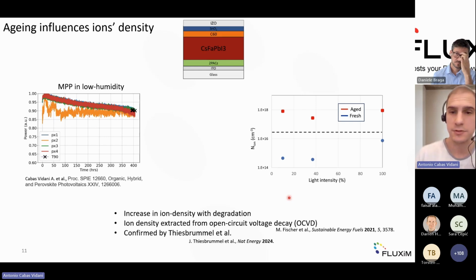So what we did, we performed open circuit voltage decay measurements where you shine a light on the sample, you turn it off, you keep the sample at open circuit voltage and see how this decays. Now with a rather complex elaboration of the data, you find everything in the paper from Fischer et al., you can extract the ion density of your perovskite layer. And what we observed here, you see on the right, was that the aged device, regardless of the light intensity, had always an ion density that was up to 2 orders of magnitude higher than the fresh device.